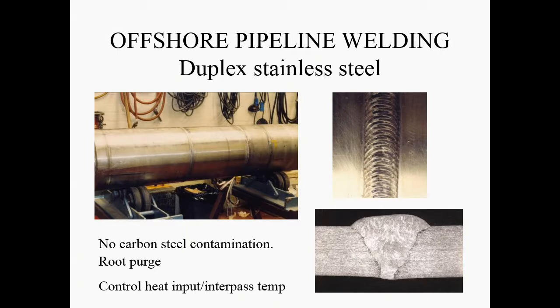Another one is, in order to prevent the oxidation, particularly the root bit for duplex stainless steel, the root bit is extremely important, the first weld that you perform. And in order to prevent oxidation, it's very common to purge the pipe in order to reduce the partial pressure of oxygen. And generally, there is a limit around 0.5% oxygen in the bore of the pipe. It's practically impossible to remove all the oxygen, and actually there are no benefits, because in air we have a mixture of oxygen